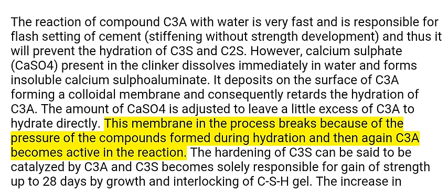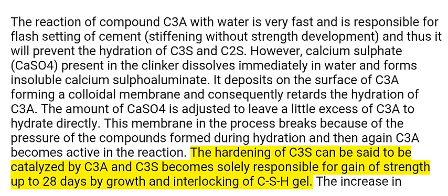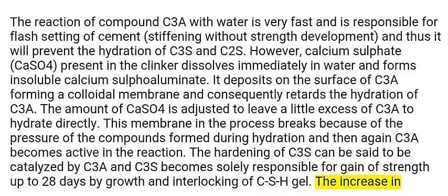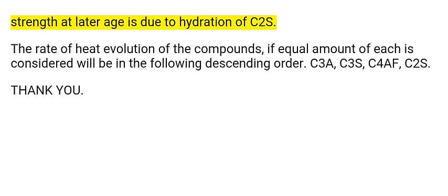This membrane in the process breaks because of the pressure of the compounds formed during hydration, and then again C3A becomes active in the reaction. The hardening of C3S can be said to be catalyzed by C3A, and C3S becomes solely responsible for gain of strength up to 28 days by growth and interlocking of CSH gel. The increase in strength at later age is due to hydration of C2S.